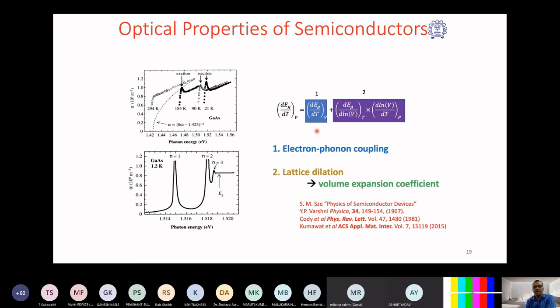That as the temperature goes high, the band gap of the semiconductor reduces, because electron phonon interactions are highly dominating. Because our semiconductors which we are using, crystalline silicon or gallium arsenide, they really do not get affected much by the presence of the temperature. However, if your semiconductor has lattice dilation being significantly high as compared to gallium arsenide and crystalline silicon, you might find the results different. And some of those kinds of examples are there.